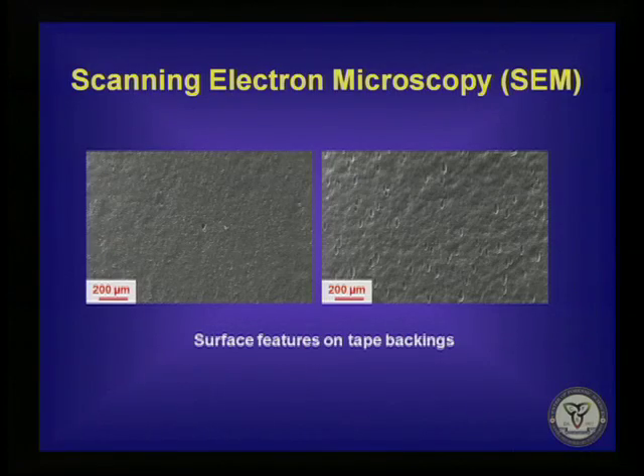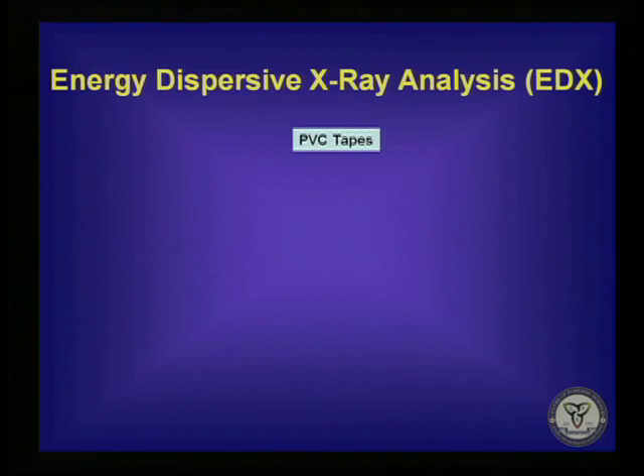The surface features we could see using scanning electron microscopy. The surface features are present on the tapes from the manufacturing process as well as from the pigment size of the fillers that may have been added to the backings. The tape on your left is less rough, and the tape on the right has more features as well as the oval pits, which are present from the manufacturing process, or calendaring marks.